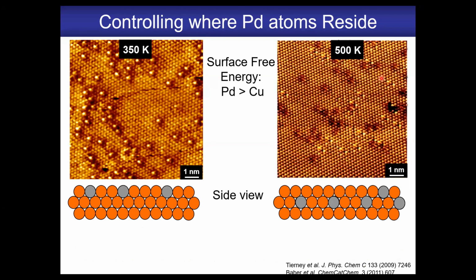And depending on the temperature we make the alloy, so just above room temperature, you get palladium imaging like bright spots. Now they're not palladium atoms on the surface because STM is so sensitive to the Z direction that they're only about 10 or 20 picometers higher than the surrounding copper. So this is showing the side view of the surface where the palladium atoms are substituted into the copper surface.